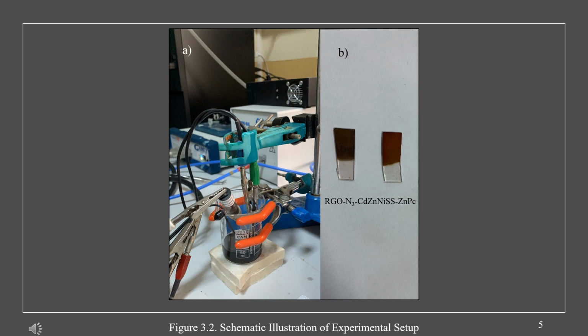The electrolyte contains soluble salts of metals in the structure of the composite: water, ethylenediaminetetraacetic acid, in short EDTA, zinc phthalocyanine, and graphene oxides. These are mixed with each other in certain volumes. The pH of the solution was adjusted with the help of sodium hydroxide. The pH was brought between 8.5 and 8.7. Finally, the obtained black solution was transferred to the three-electrode experimental setup.